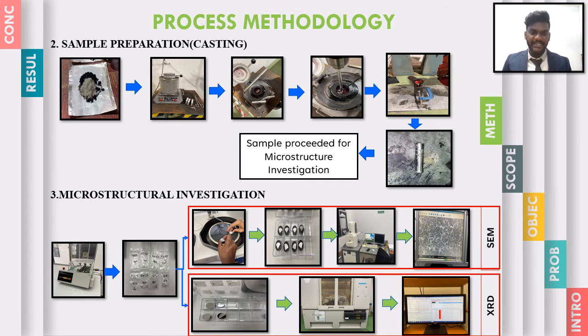So as we can see, the second step would be the sample preparation for the casting method. The sequence shows that the aluminium and also CNT were mixed by the casting method. For that, the magnesium and also CNT, where magnesium is the wetting agent and CNT is the reinforcement, were pre-mixed in aluminium foil and also rolled up in order to ease the mixing process later.